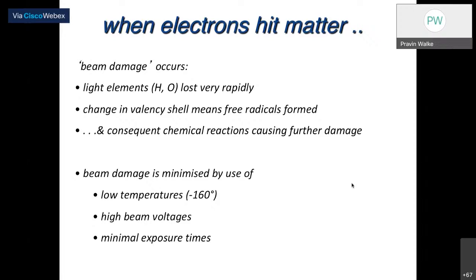The melting or boiling point of a sample can be found by TEM, but that is very delicate, and it is really to understand the properties of that. But the beam damage can be minimized using low temperature. For example, in 2017, cryo transmission electron microscopy received the Nobel Prize. So why is cryo required for the sample, especially biomolecules? At low temperature, the beam damage will be drastically reduced, and that will help us to do the imaging of biological samples. Then we need to improve the high beam voltages, and we need to have the minimum exposure dose in order to avoid those things, right?